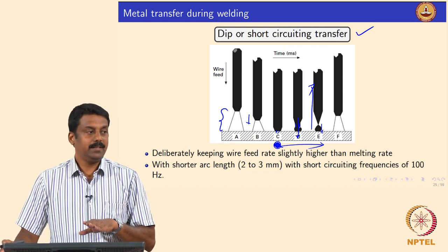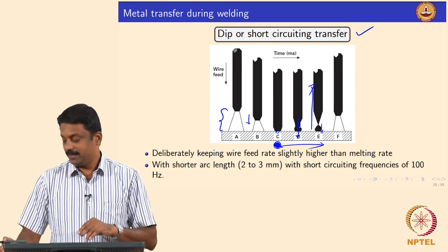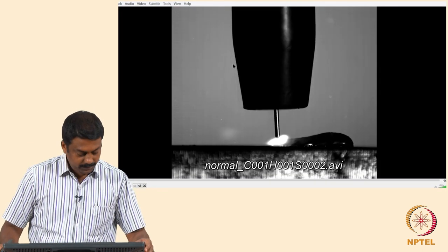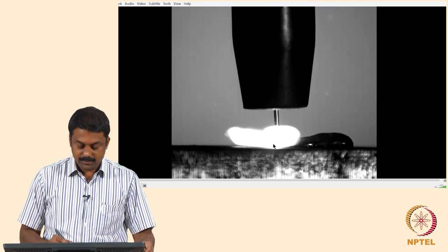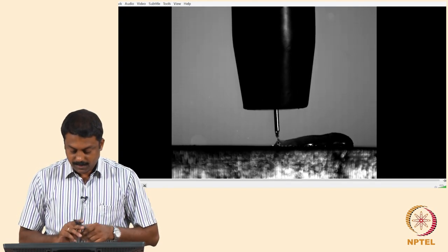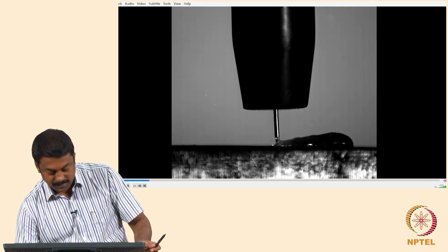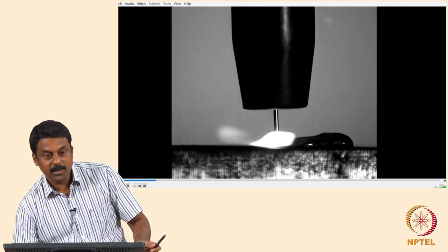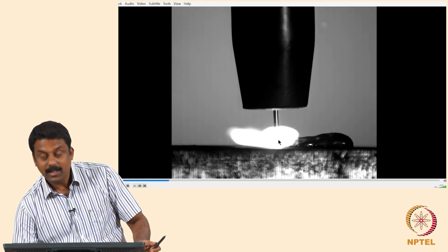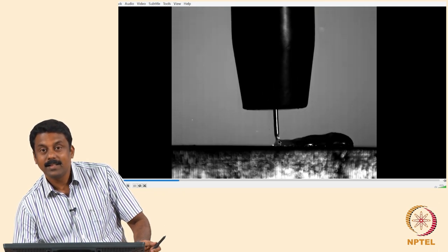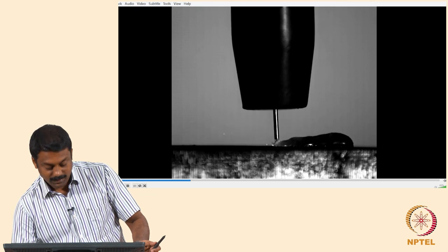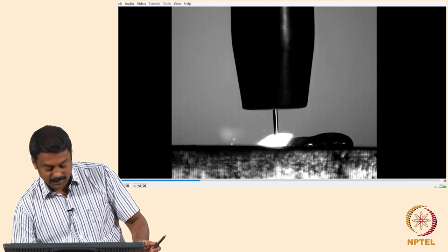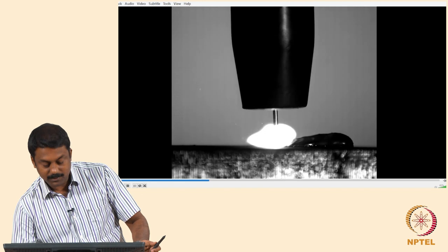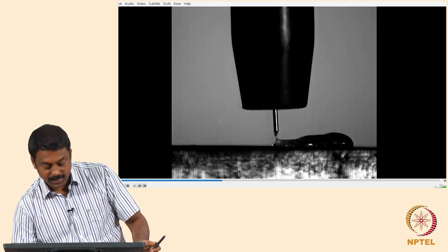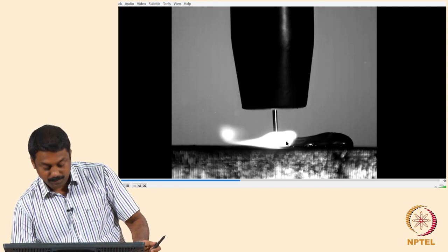Right. It's clear. I will show you a video. It will be very clear. So, you see the transfer. What is happening here? You have an arc. Transfer happens by the short circuiting, and during the short circuiting event, there is no arc. You see that? So, you establish the arc within the arc length, and then you switch off the arc the moment the short circuiting happens, and then you transfer the droplet by the surface tension of the liquid pool.